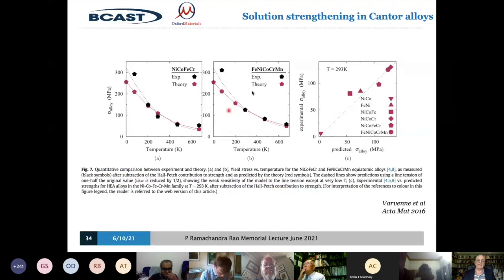So the basic idea, to put it into technical language, is that it's not the Peierls stress, and it's also not the work hardening, although it's got great work hardening capability. But the high strength basically comes from the difficulty of pushing dislocations through the lattice because of the strain fields in the local distorted lattice.